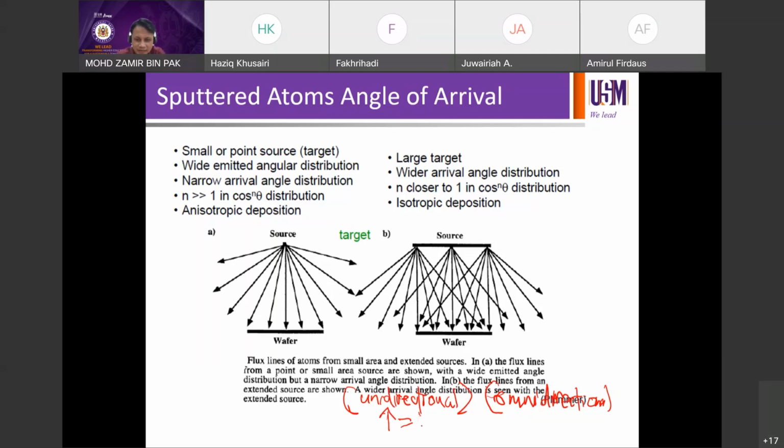Evaporation, right? Evaporation, paling unidirectional. That's it. Thermal evaporation, electron beam evaporation, line of sight, it goes straight up. Kalau dia ada cone pun dia buka pun just very little. It's highly directional. That means if you have features on the wafers, if you mount at some angle, perhaps if it's not well rotated, then you will suffer from shading effect on the side of the structures, right?